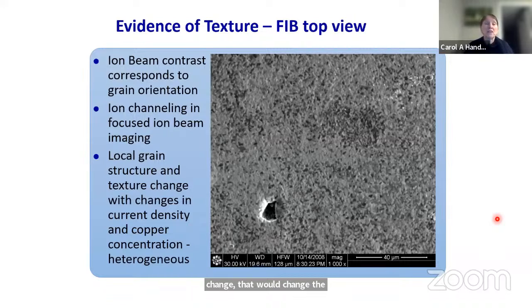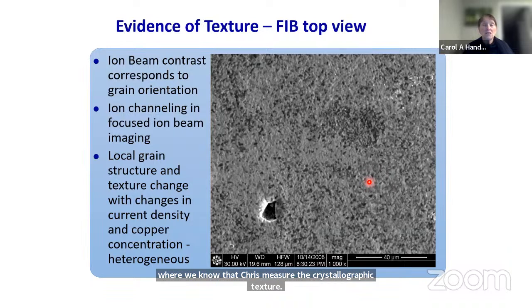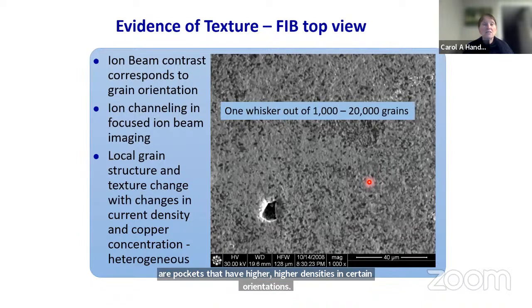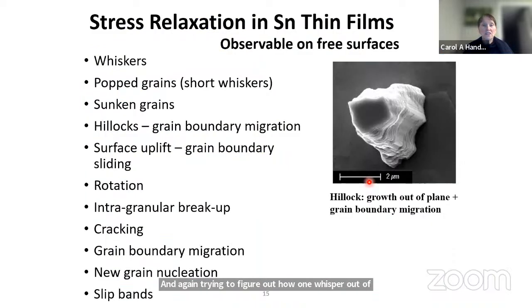So here's an ion beam contrast image that shows grain orientation. You can see here the darker ones are all grains in the same orientation. So even when we're looking at something where we know the measured crystallographic texture, there are pockets that have higher densities of certain orientations. And again, trying to figure out how one whisker out of 1,000 or 20,000 grains forms has been challenging. So here are just some of the microstructures that one sees.